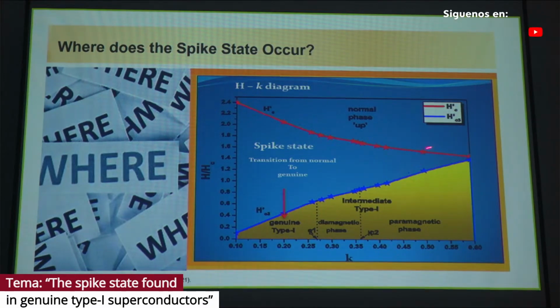In this case, this is where you see the jump in the magnetization curve, the first jump in the magnetization curve. But when you're decreasing, for instance, in the same material, 0.5, now it is in the normal state. Let's suppose I am decreasing the applied magnetic field. It's normal state, normal state, normal state. Nothing happens when it crosses the red line again, and this is not new, because it is in the Tinkham textbook. So we cross this line, nothing happens.